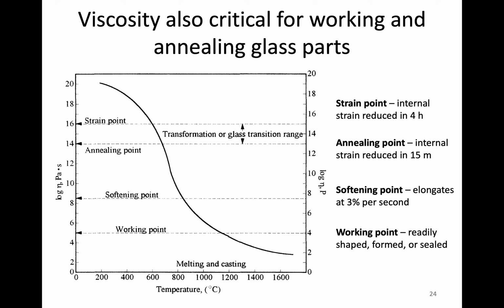All right, this is a pretty typical plot of viscosity as a function of temperature, particularly for glass. Again, we have log viscosity, so when you see a change of 1, that's a very large change because it's a log scale. Keep that in mind. And then temperature here as well. This is what a typical curve would look like for the viscosity of a glass, and we have it broken down into multiple regions. Again, I like to start at the highest temperatures. In this regime, this is where it's melting or casting. It easily flows and we can process it at that point. So the highest temperatures are where that's happening.